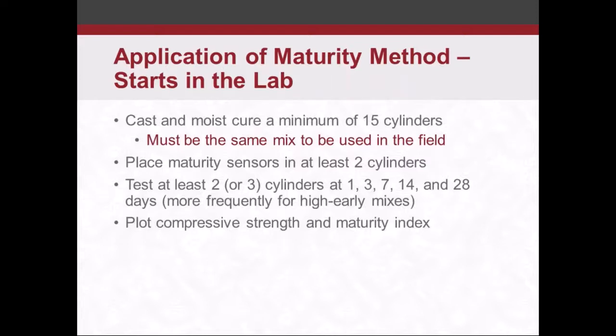First thing we do is we cast and cure a minimum of 15 cylinders in the lab. This is done in the lab, and it's got to be the same mix that's used in the field. So if you've got a 5,000 psi mix, you want to load it early, and you want to estimate what the strength is. First thing, using the maturity method, you've got to establish this maturity curve in the lab by casting these 15 cylinders. We put maturity sensors in at least 2 of the cylinders, that measures our time and temperature.